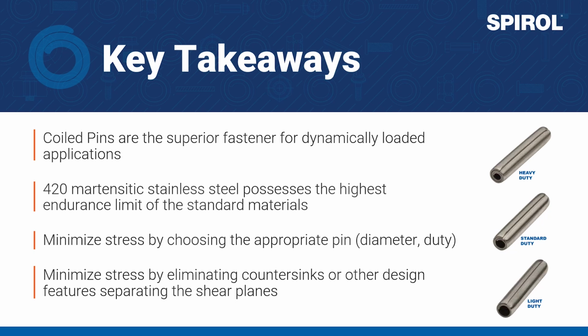This may have been a lot to ingest in one sitting, so let's summarize the key takeaways here. First, we've demonstrated that coiled spring pins are the superior fastener for dynamically loaded applications. So whenever you identify that an application will have a changing force over time, consider using a coiled spring pin. In regard to pin material, 420 martensitic chrome stainless steel will provide the highest endurance limit as compared to our other standard materials. This includes high carbon steel, even when comparisons are made in oil-rich environments where corrosion is not of concern.